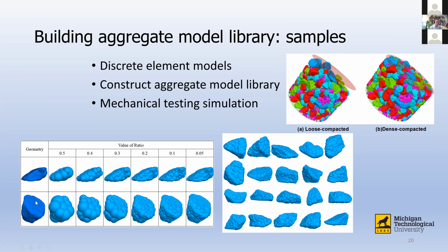So in order to simulate what the stones look like, we get some kind of numerical images of the stones. And we use different models to represent them. You can see poor resolution, better resolution. You can go on and on to make it very accurate. With that, we generate an aggregate model library. So we create those through different techniques, and we can do a lot of simulations to see what kind of gradation is good. How much percentage of stones versus, let's say, bigger aggregates versus sand? What's the proportion we should have so that we have a better design?